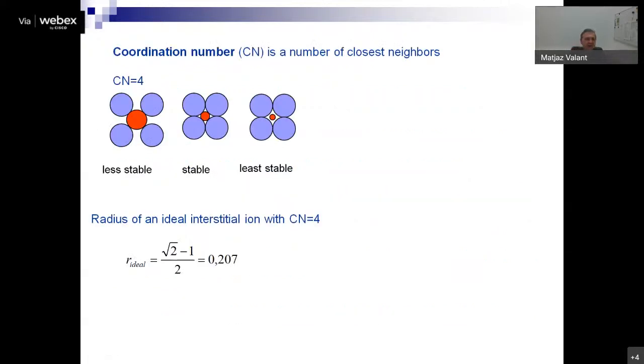So let's consider these two species, red and blue, and how they can put themselves together. Now we are in two-dimensional space for the sake of simplicity. So of course the blue will want to encompass the red atom in this way in two dimensions, and we see already that we have one situation when the red atom perfectly fits into the vacancy here. In another situation it is too big for this vacancy, and in another situation it is too small. So when it's too big, it will allow these blue atoms to oscillate around, and you see this bond is not present anymore. So this system is less stable than this ideal system when all is nicely packed together.